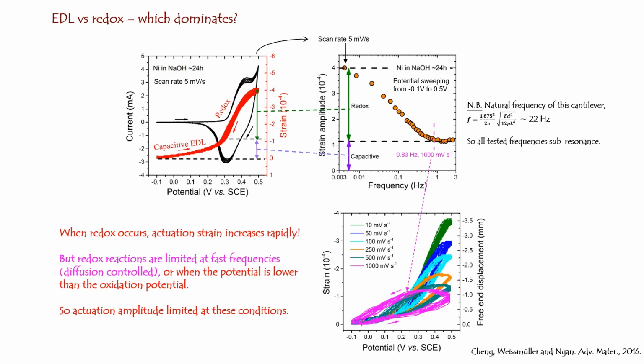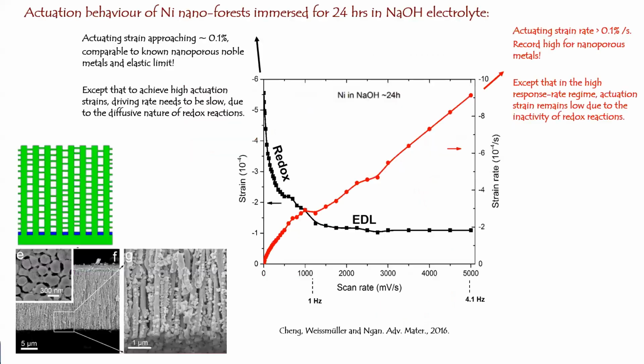However, whether redox can occur or not depends on, of course, your voltage range, but also the scan speed, because this is diffusion controlled. Here you see the scan plot at different scan speeds. Only if you scan slowly, like 10 millivolt per second, you can have the green, and that can have the redox, which is this big elevation. If you scan very quickly, 1,000 millivolt per second, that curve remains very low and flat, so you only have the EDL dominating. That's what this graph summarizes. So that's the scan rate.